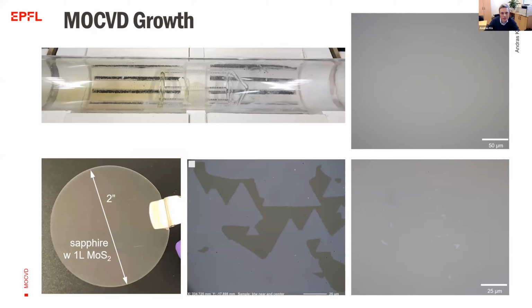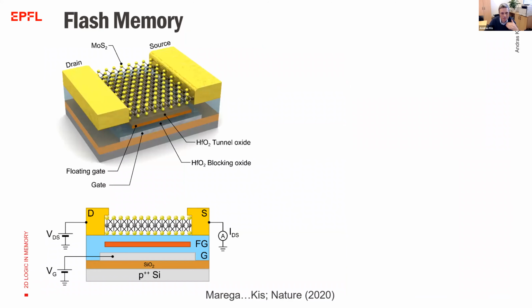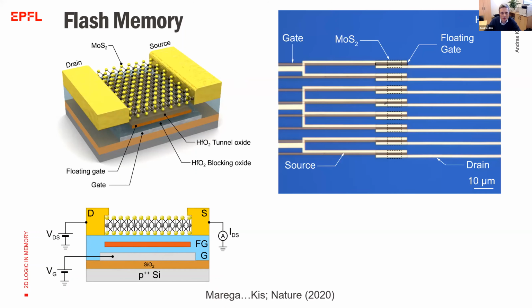And then we integrate these high quality materials onto structures that are prefabricated on the wafer scale, where we have gate electrodes, which we use to control and switch the transistor devices. But in addition, we also have floating gate structures. So these are very thin metallic films in which charge can be stored, and then this stored charge can influence the conductivity of the 2D film.